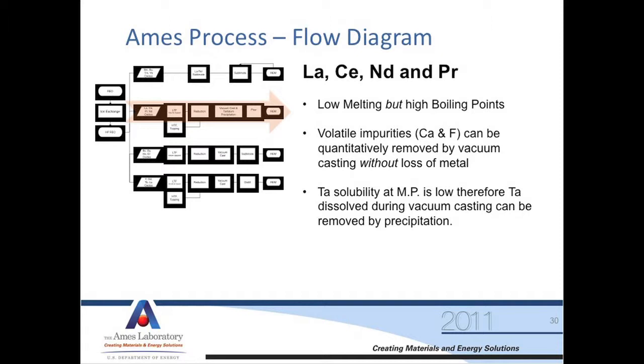Next group, the light rare earths lanthanum, cerium, neodymium, and praseodymium, are the next easiest to make. If you remember from the vapor pressures, they had the lowest vapor pressure, i.e. highest boiling points, and they were very low melters. We can use that to our advantage because we can vacuum cast these without loss, meaning any impurity that's volatile, we melt it under vacuum and it comes out, leaving the metal we want behind. The tantalum solubility is pretty low, but because the vapor pressure is so low, we don't distill or sublime. We do what we call pouring.